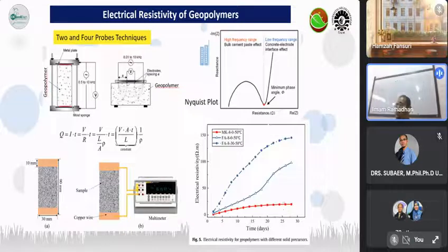and then you can measure the electrical resistivity as a function of time by using a very simple experimental setup shown here. So this is one of the formulas that you can use in order to measure the electrical resistivity.